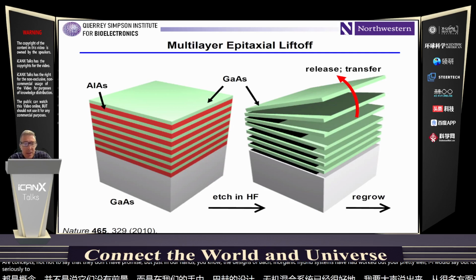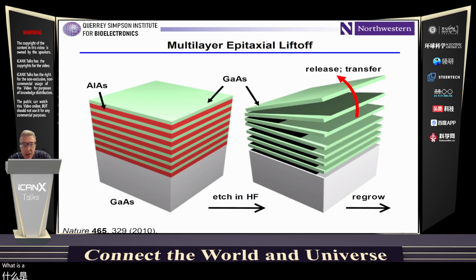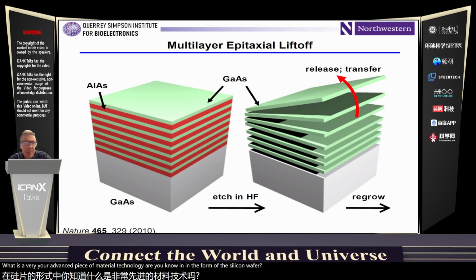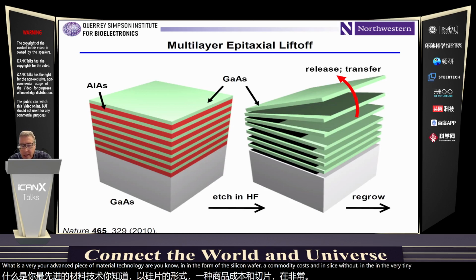In this case, we're using a multi-layer epitaxial liftoff scheme where we grow, using MOCVD techniques, alternating layers of aluminum arsenide and gallium arsenide. And then you etch down through those stacks vertically to expose the sidewalls. And in this case, you use concentrated hydrofluoric acid to eliminate the aluminum arsenide without etching the gallium arsenide. There's an etching rate contrast of about a factor of 1,000,000. So gallium arsenide then is lifted off the source wafer in bulk quantities in a similar kind of multi-layer scheme, much different in the details compared to what I showed in the context of silicon in the previous slide, but conceptually similar. You're using a wafer as the basis, and in this case, you're just using the wafer catalytically, in a sense, because you can reuse it for additional cycles of epitaxial growth. So you can do all of this.